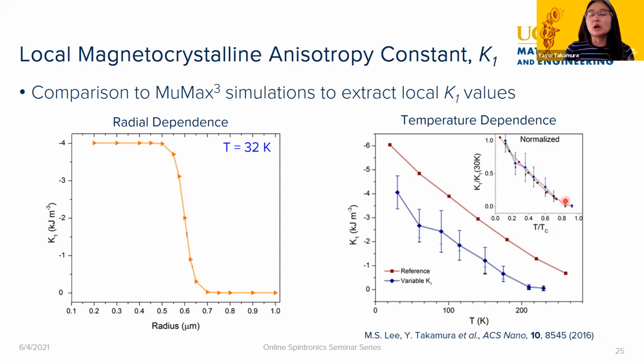So basically what we could say is that, within these nanostructures, we actually are getting bulk, or close enough to bulk-like, magnetocrystalline anisotropy. But we could also then map these magnetic parameters locally, with sort of 100 nanometer spatial resolution, as a function of temperature, and as a function of position within the nanomagnet.